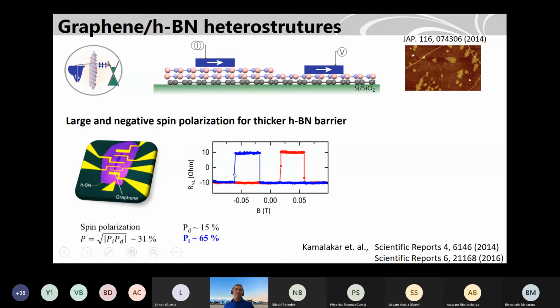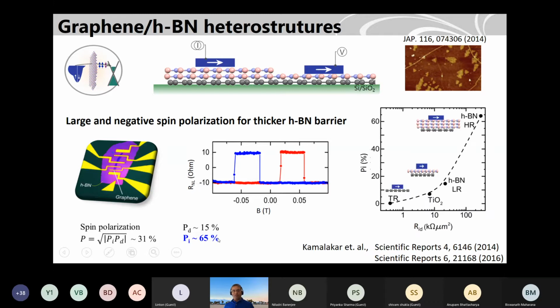So what we see is a very good result when we have a trilayer boron nitride at one point. So we get very good signal, up to 20 ohms here. And if we translate that signal into the spin polarization of the contact, because we know the polarization of the contact for the single layer, and by doing different devices, also putting different contacts, because as you see here, we have different contacts, and you can find out the spin polarization of each contact by comparing with similar resistances. So the polarization with the multi-layer comes out to be 65%, which is quite large.